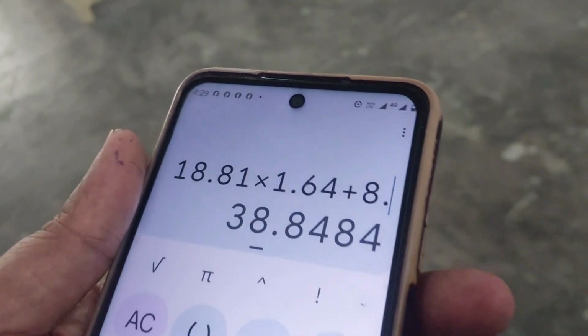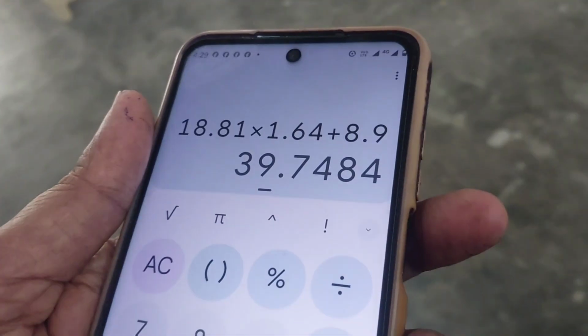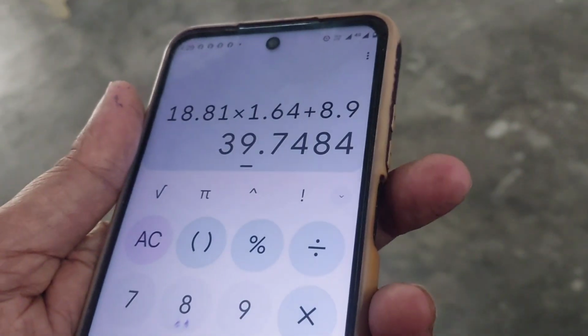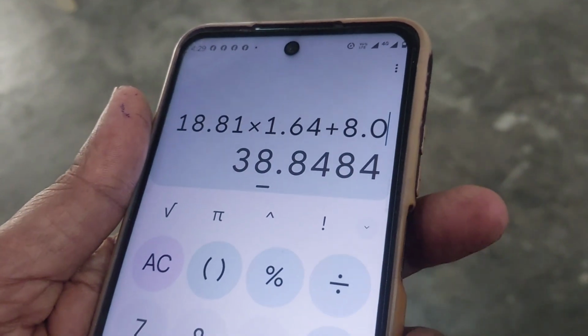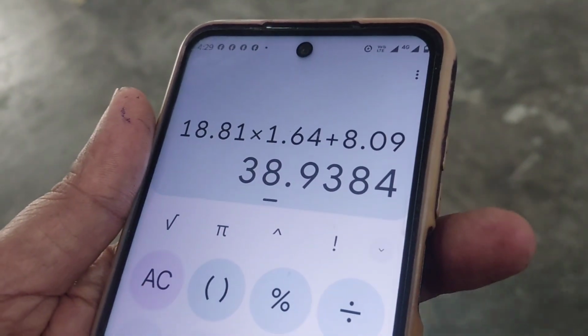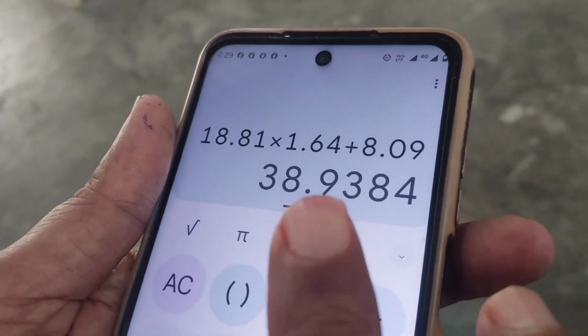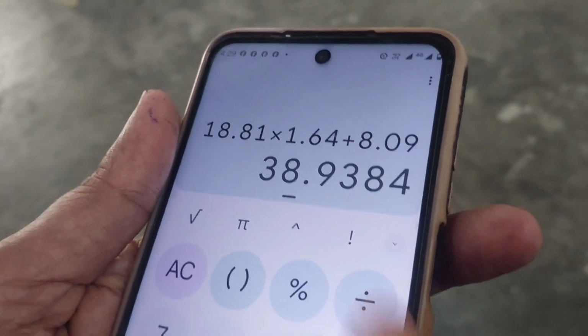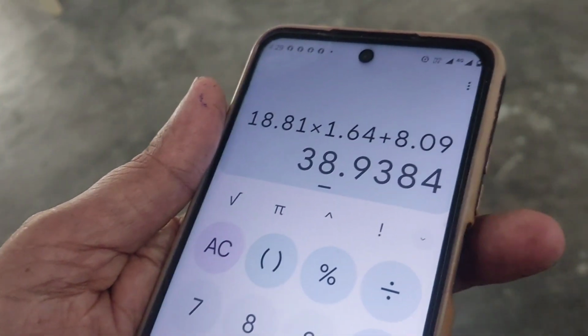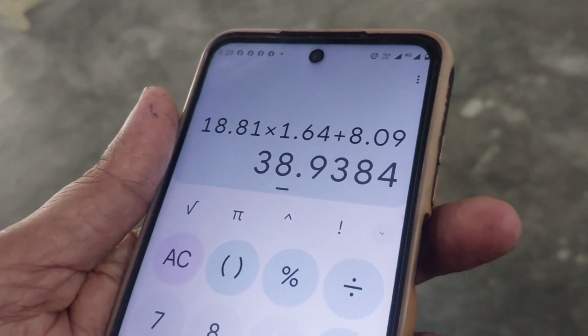You can see 39.74 MPa, that is Newton per mm square. So this is the average compressive strength of the standard cubes, after doing the calculation, for cubes cured by the accelerated curing method, which is valuable.